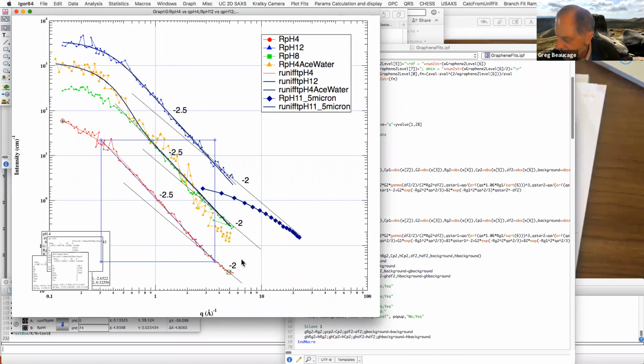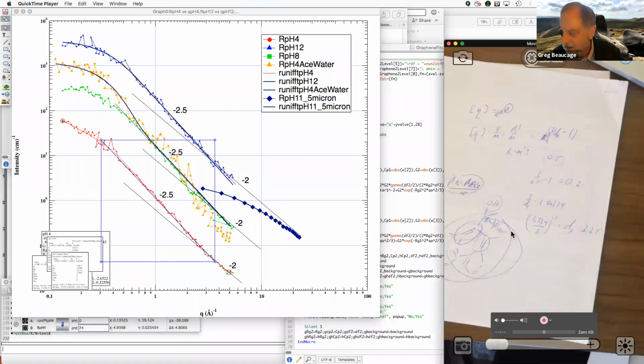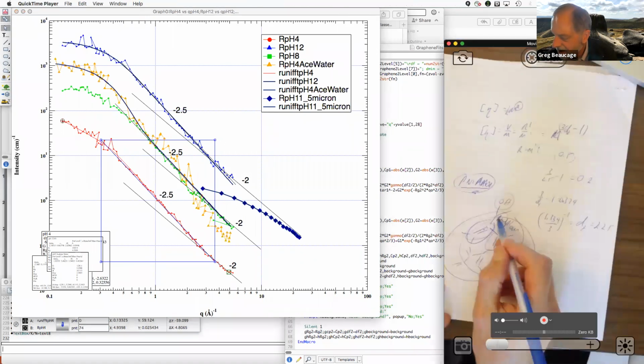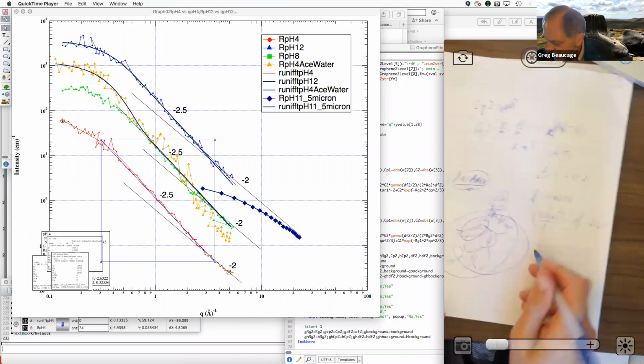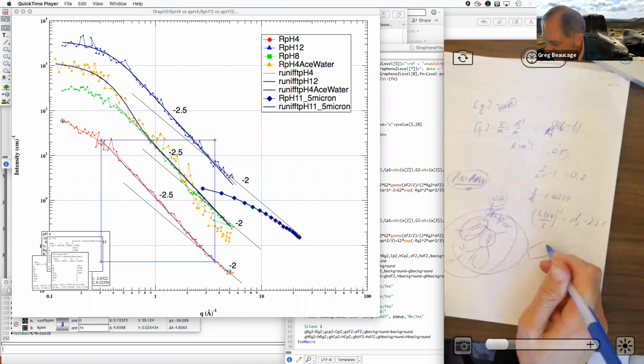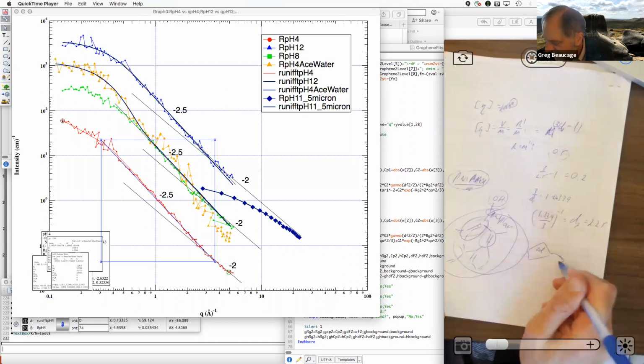right? Or if you can draw it that way, every one of these is planar. So everything they link to, as long as it's conjugated, double, single, double, is going to be planar. So the entire thing has to be a sheet. You can't bend that until you stick in an oxide, a hydroxide group. And then all of a sudden that can bend. Oops, I'm not showing this thing. So it can bend once you put in the hydroxide group. So it's going to be made up of primary or persistence units that are 2D, and then it's going to transition over to this kind of crumpled thing.